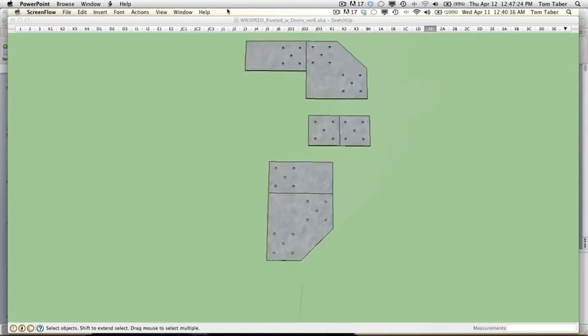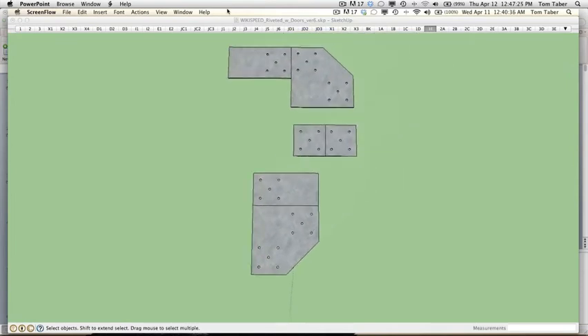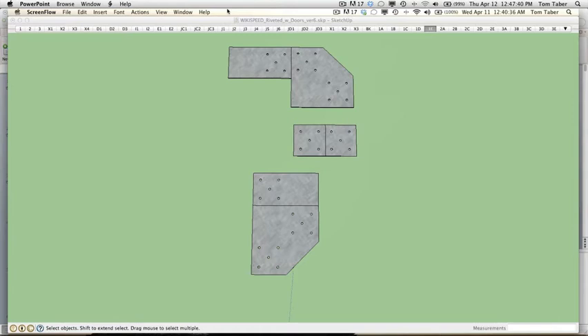And because these aluminum blocks are solid, they actually create a heat sink that makes it easier to weld them together. So it actually takes some of the heat away from that joint and just makes the welding process much simpler. By screwing all the plates in, you know that they're exactly lined up and they don't distort during the welding process. And so then when you unbolt it, pull those bricks out, we actually have the unit that's dimensionally correct can be used as a modular connector. Then here's the different plates that are used for this particular connector. And you can see these are very specific shapes, specific drill patterns. These can be created on CNC.